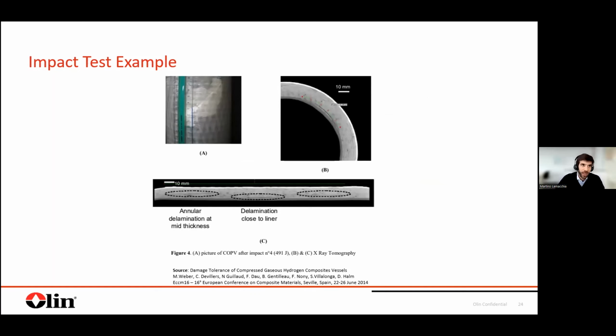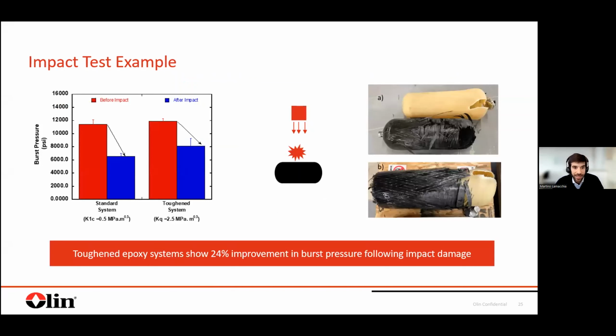The key high-level concept we would like to transmit here is: not every matrix is the same, not every epoxy is the same. Different grades for different applications and requirements. If you take a look at the graph in the next slide, you will see, for example, that between a toughened system and a standard epoxy system, you can have a huge difference in burst pressure. So on the left, a standard system used to make a tank, you see the burst pressure before and after the impact test. On the right, a toughened system, again, burst pressure before and after. You see that the Olin toughened epoxy system is showing a 24% improvement in burst pressure following the impact damage.